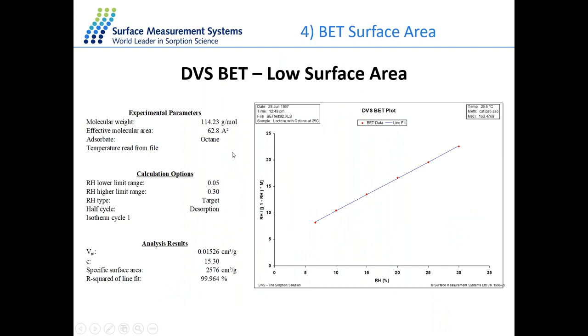So once you carry out your BET surface area experiment, in this case, we're looking at octane as a probe molecule. We also have to plug in some known information, such as the effective molecular area, and the molecular mass in grams per mole of our sample. And what we can do is carry out the experiment from 0.05 to 0.3 relative humidity. So what we've done here in different stages is increase the relative humidity up until about 30%. And what we can obtain is our BET plot. So here we have our analysis results. We have the BET surface area and the R squared. So this is what you typically obtain after carrying out the BET surface area experiment.